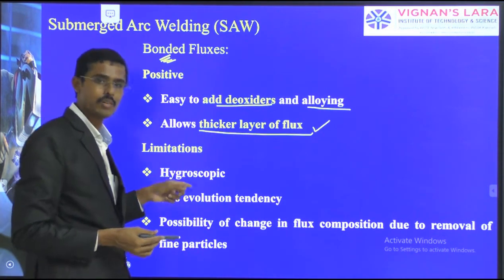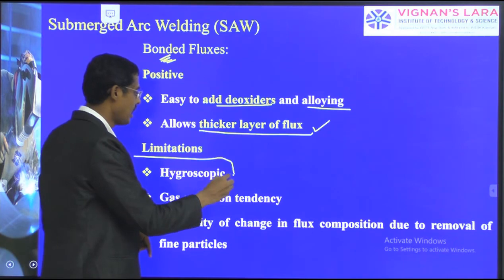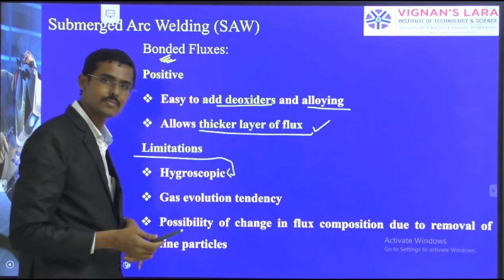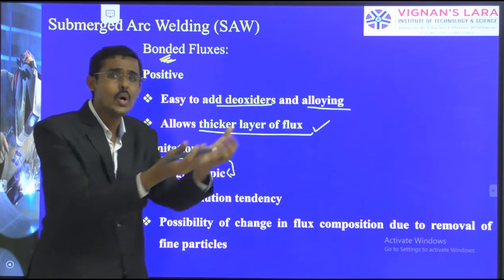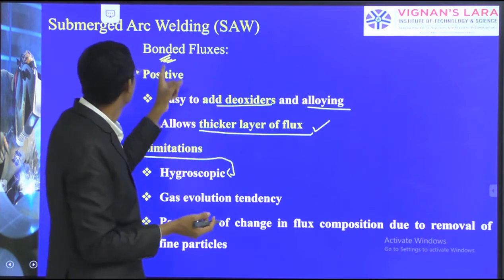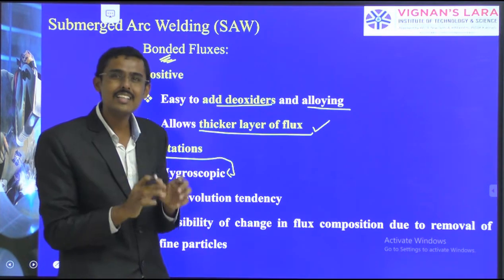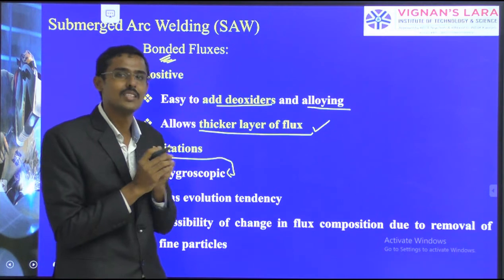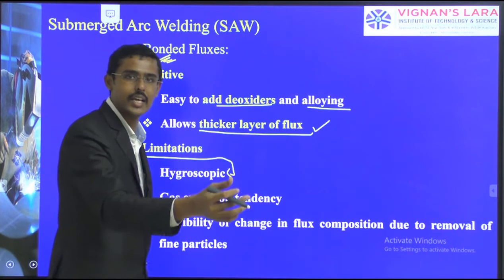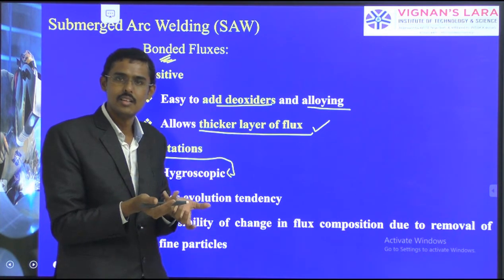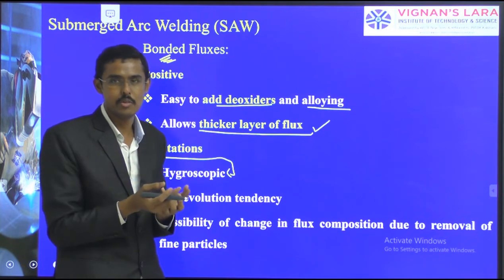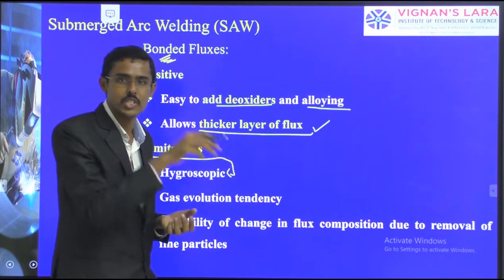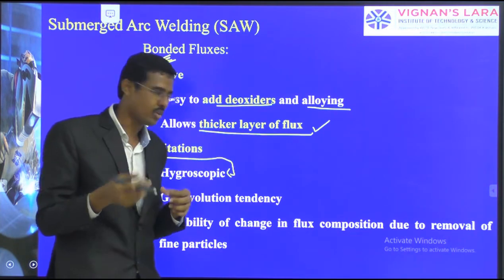Limitations: hygroscopic. We are talking about limitations. See, hygroscopic comes here. What is hygroscopic? Tendency to absorb moisture. Here, these bonded fluxes have the tendency to absorb. Then what happens? When it is exposed to air, it becomes wet. If it is wet, hydrogen embrittlement automatically comes into the picture. So this is one of the disadvantages.